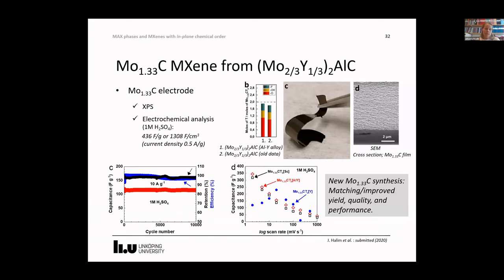So by starting with an aluminium yttrium alloy for the IMAX synthesis, and by optimizing the etching process, we've synthesized a MXene with matching or even improved yield, quality, and performance compared to the MXene from scandium-based IMAX. And altogether, this is important in terms of reduced waste material, use of more abundant elements, lower cost, and therefore higher applicability.